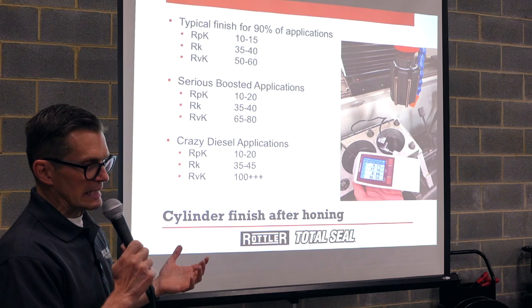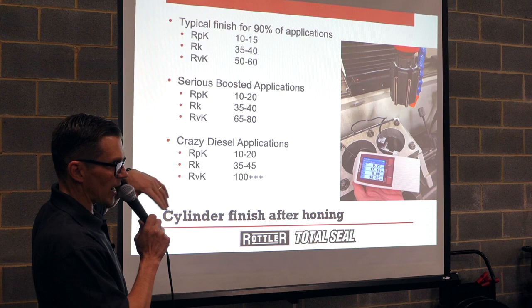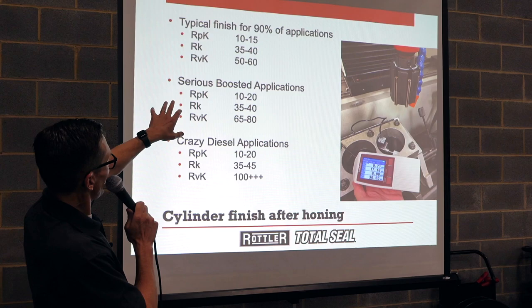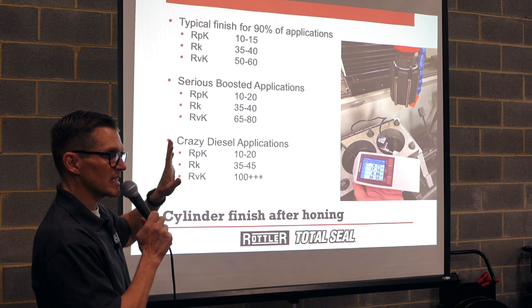So some guidance numbers, if you're still using the old profilometer, the Mitutoyo, you really can't look at the graph because the screen auto scales. It doesn't really tell you what you need. So you're going to have to kind of fly by the numbers, which is better than flying blind. Typically, say 90% of your applications, you're going to want an RPK somewhere in that 10 to 15 range, RK in the 35 to 40 range, and then RVK in the 50 to 60. That's a pretty good finish. It'll work for most applications.